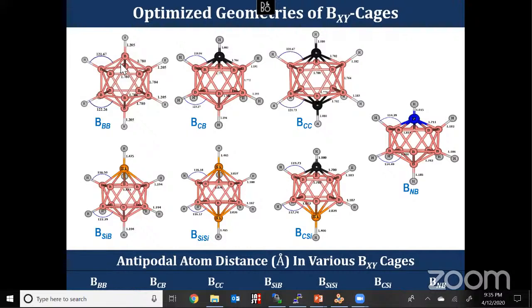For a clear view, I removed some of the hydrogens here, but the hydrogens are really present during the calculation. In the antipodal position, I introduced mono as well as dicarborane. When substituting with a single carbon, the 2- charge is reduced to 1-. When I substitute with two, the cluster is neutral, and with nitrogen also it's neutral. We measured the distance between the antipodal atoms of the pristine as well as the heteroatom-substituted clusters. There is a change in the cluster, but it does not deform the backbone of the structure totally. There's a deformation, but not too much.